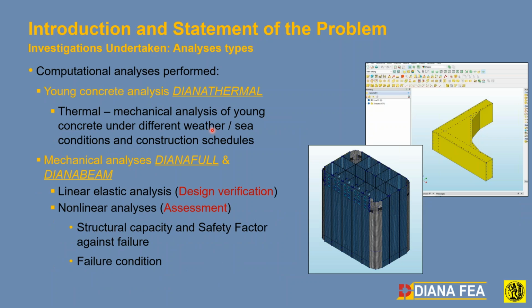So in order now to find out what really happened and evaluate, we devised an analysis set using Diana. We did basically 2 different analyses. One was because the caisson was sunk into position into the sea during 3-4 days, and then it was continuously cast through slip form, but sunk. The bottom of the caisson was continuously inside the seawater. We did a young concrete thermal analysis, a maturity analysis using Diana, using the material properties of the as-built conditions.